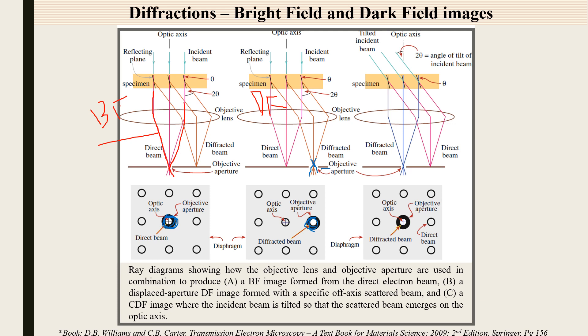The third example is the centered dark field image: the diffracted beam is brought to the center — like a bright spot position — through objective aperture adjustment, giving a centered dark field (CDF) image. These are the three images we can obtain using a transmission electron microscope: bright field, dark field, and centered dark field, by adjusting the objective aperture relative to the direct or diffracted beam.